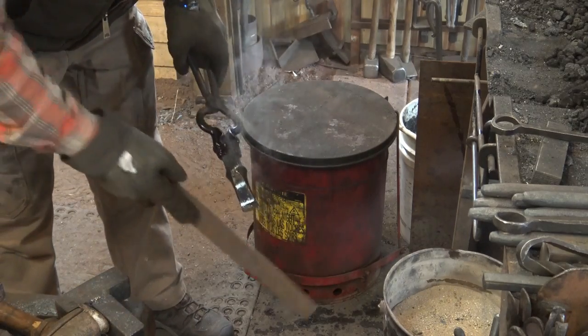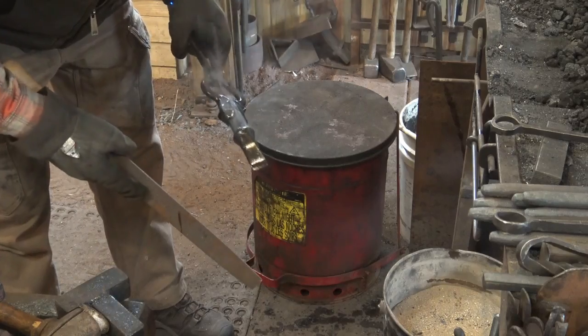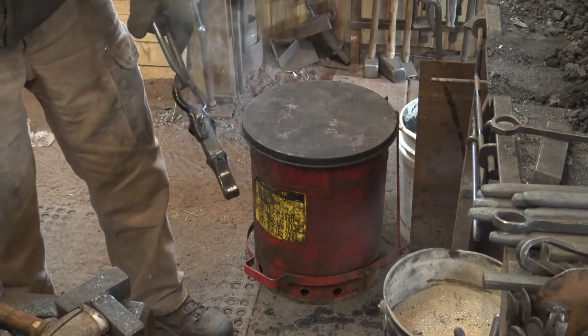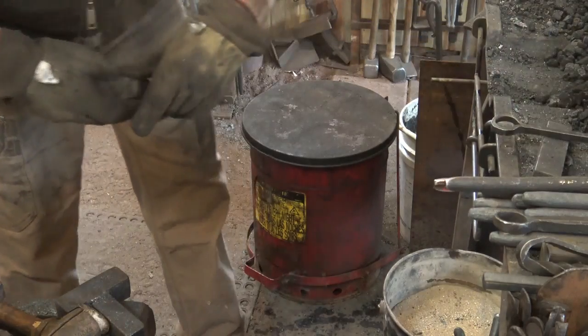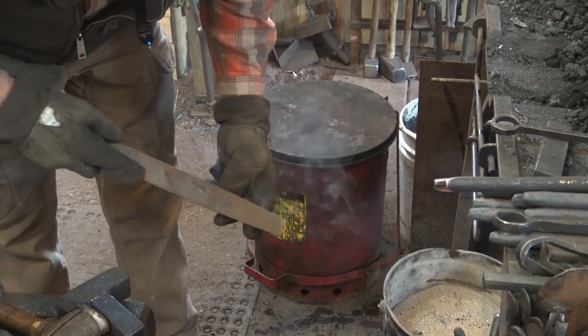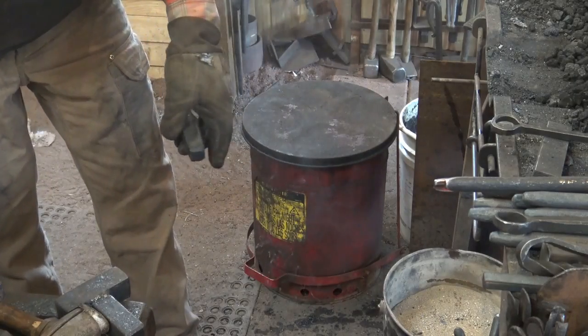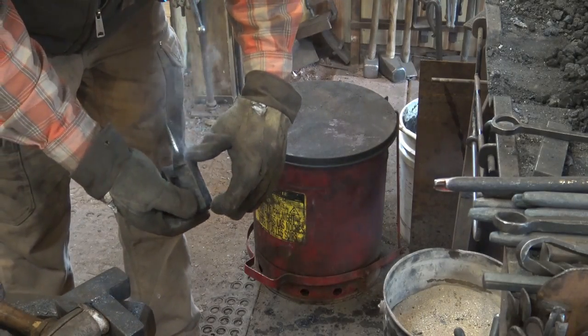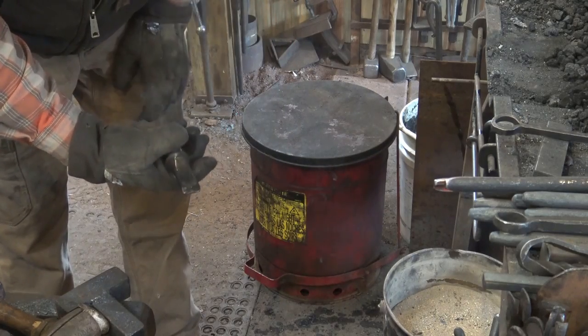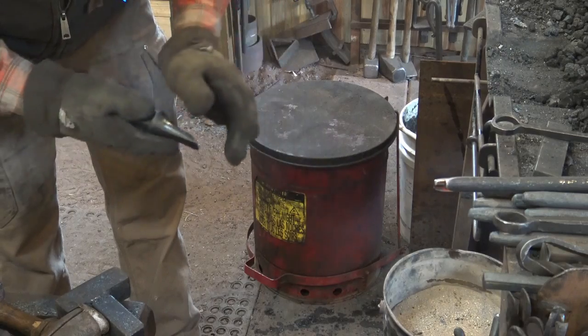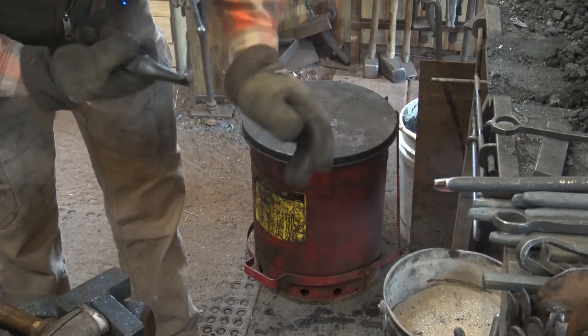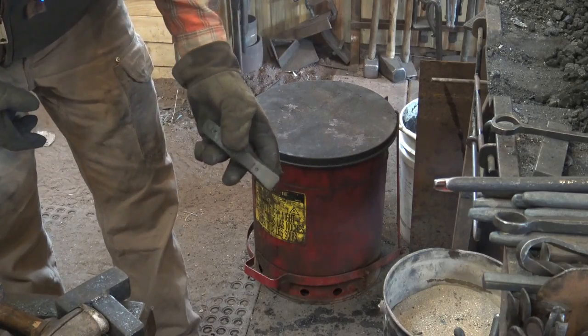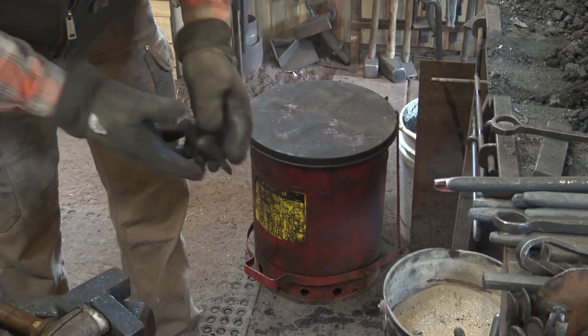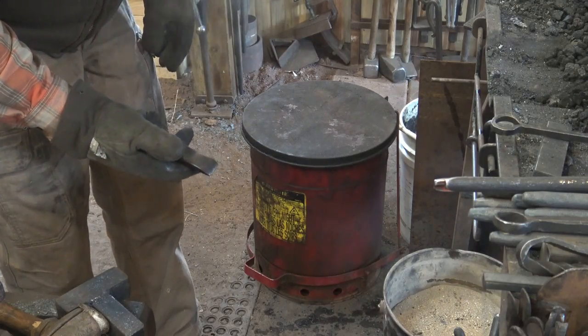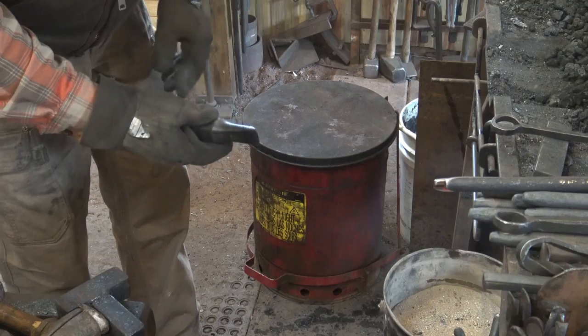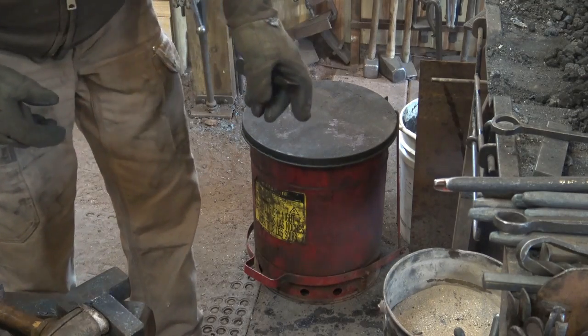So we'll do the same thing. That file just skates off of that. And bites very nicely into that end. So again, this part of the tool is fairly soft, and this part of the tool is good and hard and needs to be tempered. And I'm going to temper it at the same temperature that I'm doing the other one. 4140 actually can temper a little bit lower than that, but for a hardy I don't think that's going to hurt it. And after we've used this a few times with hot steel on it, it's going to temper way back anyways.